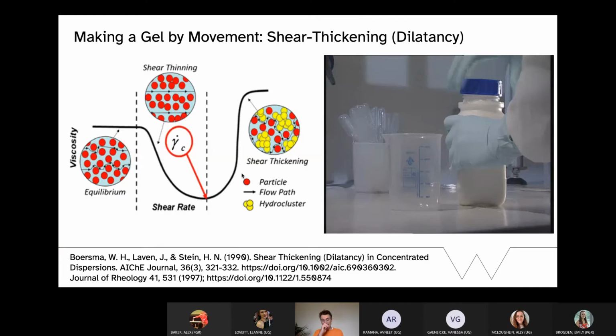Now, another really interesting property is the viscosity of these little ping pong balls. So for example, if you would like to use it as a paint, if you wouldn't touch the material, you want the viscosity to be relatively high. So if you would paint a vertical wall with it, it wouldn't drip down the wall. However, if you actually are painting, you want the viscosity to go down. So if you apply a force to it, you can get an effect which is called shear thinning, so the viscosity drops.